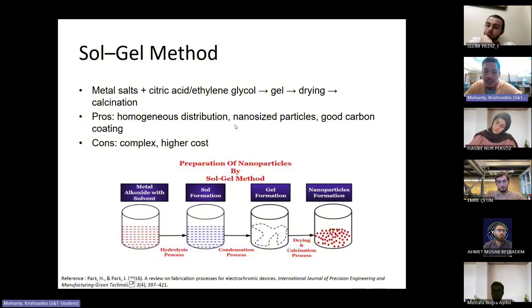Again, because of this, the particles can be nano-sized because it's a solution itself, and it depends on how you dry your solution, the particle size is going to come about. We can get good carbon coating with this method. It can be complex because we're getting a gel or a slurry. We are not getting a direct solution, and it can cost high because of the materials itself and the process cost.